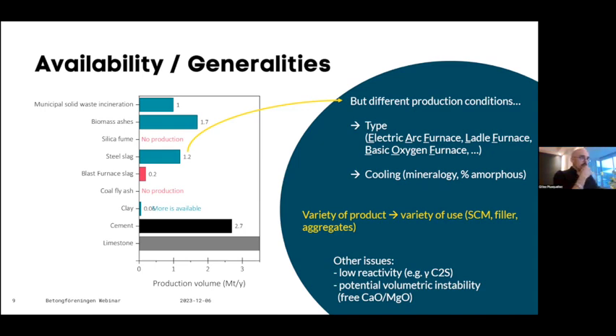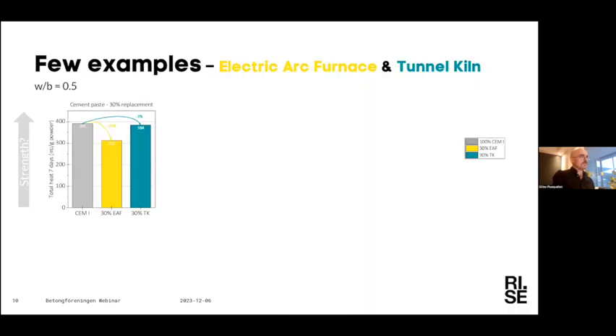Some issues have also been indicated when we talk about SCM, which I'm focusing on today. It's a lower activity. For example, you can have the formation of gamma C2S, which is known to be not reactive. So if you have a lot of this phase, it's a bad sign, at least for use as SCM. Or the expansion problem if you have a lot of free lime or free magnesium oxide. I'm going to give some examples now of what we did with a sample coming from an electric arc furnace and tunnel kiln, so from the same plant, but a different product line.